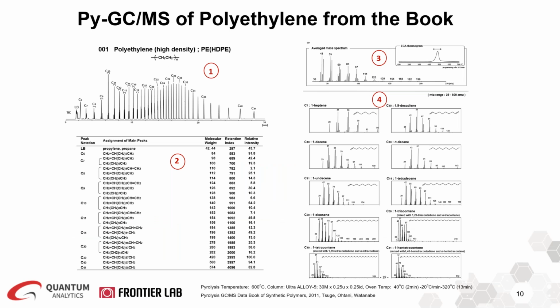Here is an example page from the book for pyrolysis GCMS of polyethylene. You can see the pyrogram of the polymer that is performed at 600 C as shown as number 1 category. Number 2 category is the peak assignment table together with molecular weight, relative peak intensity, and the retention index. Number 3 is the EGA thermogram that was performed from 100 to 700 C, 20 degrees per minute, as well as the average mass spectrum of the EGA. And number 4 category is the mass spectrum of the top 10 major peaks. So F-Search is a search engine software that contains all that information from the book.